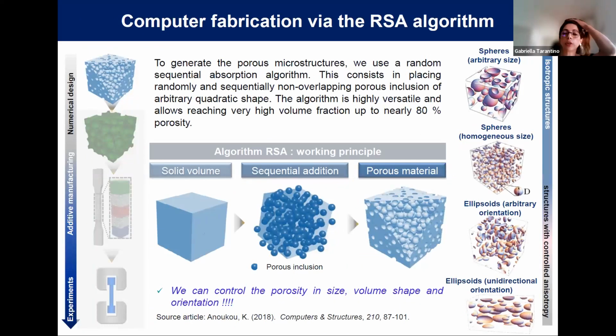Now, the tricky part of the random metamaterial is how to design them numerically. Because like all metamaterials, they have first to be designed, and then their STL model is generally given to the 3D printer for fabrication. We use a random sequential absorption algorithm, which is a very versatile algorithm, and which we have developed over the years. Basically, its working principle is pretty straightforward. It consists in placing random inclusions in an arbitrary matrix, so they are heterogeneously dispersed in a solid volume. The advantage of this method is that we can control the particle shape, the particle size, and eventually the orientation. So basically, we can have a very large palette of microstructures, which span from isotropic to anisotropic.